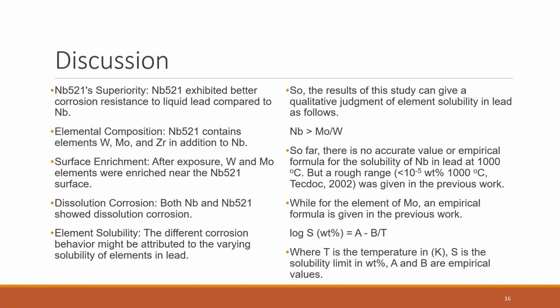After exposure, tungsten and molybdenum elements were enriched near the niobium alloy surface, and both niobium and niobium alloy showed dissolution corrosion. The different corrosion behavior might be attributed to the varying solubility of elements in lead. So, the result of this study can give a qualitative judgment of element solubility in lead as follows.